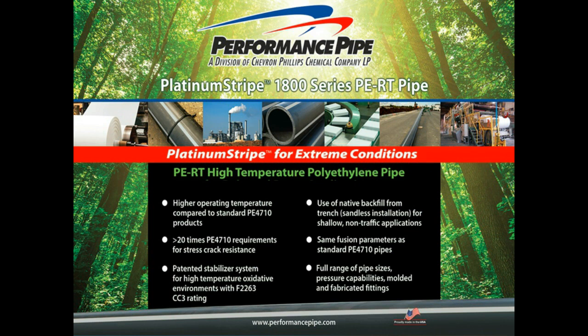I had a question on whether it can be used in lining applications, and certainly the answer to that is yes. Just like standard polyethylene, it can be used in slip lining, swage lining, as well as some other tight fit liner applications. Where it would really come into play is where you need better performance characteristics than standard 4710. As Wes alluded to, this material is very well stabilized, so it has the highest chlorine category listing of CC3. So it's very resistant to higher oxidative conditions if those were in the flow stream, and this would certainly be a candidate where you've got an aggressive fluid in a pipeline that needs to be lined.